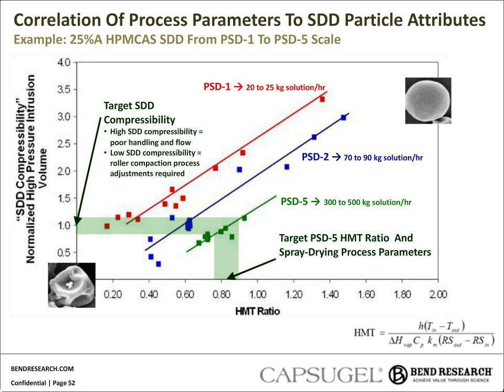As the HMT ratio plotted on the x-axis increases, the rate of heat transfer into the droplets is faster than the rate of mass transfer out of the droplets, and the SDD density increases. So to identify process parameters to achieve the target normalized SDD compressibility ratio of 1, which in this case was ideal for this particular SDD in terms of its downstream roller compaction process, you can use the HMT correlation at any scale. So for example, for a PSD5 dryer, a target HMT ratio of around 0.8 is desired, and that HMT ratio is calculated using the key thermo parameters that we reviewed today.